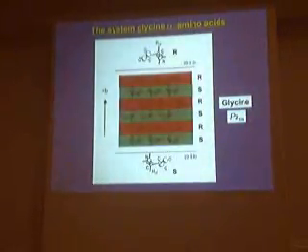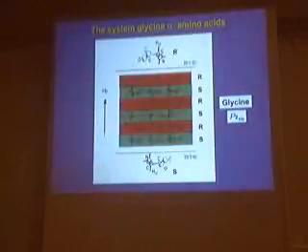Okay? So the first thing that we are going to do now is glycine. And I say glycine has three polymorphs. The most stable polymorph which crystallizes from water is centrosymmetric. Beta form is metastable, it's polar, enantiomorphous. Gamma is metastable.